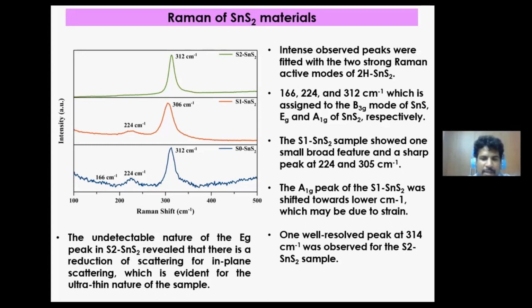In-plane scattering is evidence for the ultra-thin nature of the sample. That is the primary thing. And the shift may be due to the strain of the samples. So in our TEM analysis, we have seen orbicular structures formed inside the material, so that the strain may be confirmed with this Raman analysis that is represented in red color.